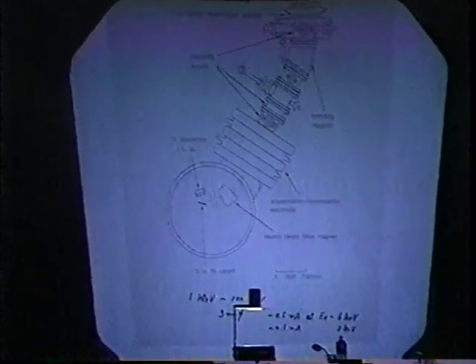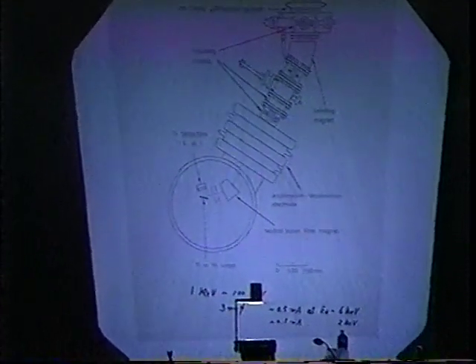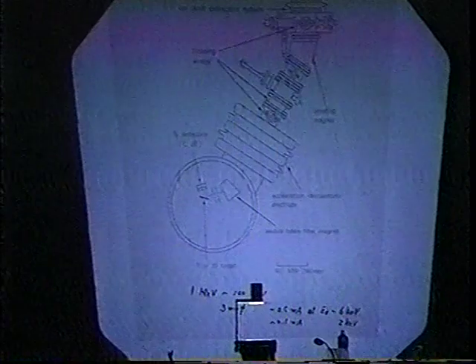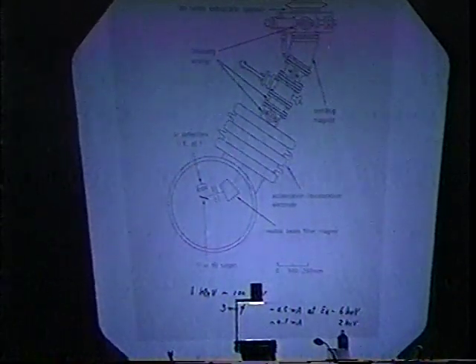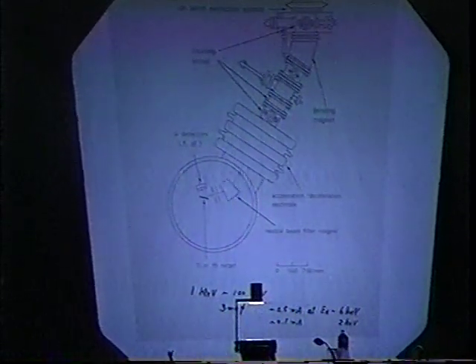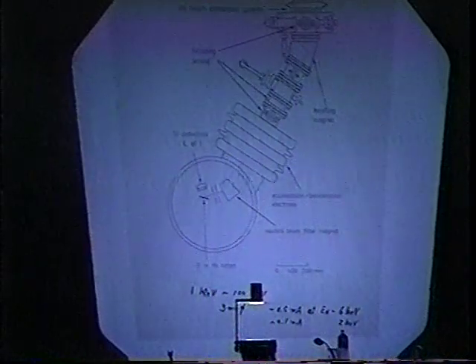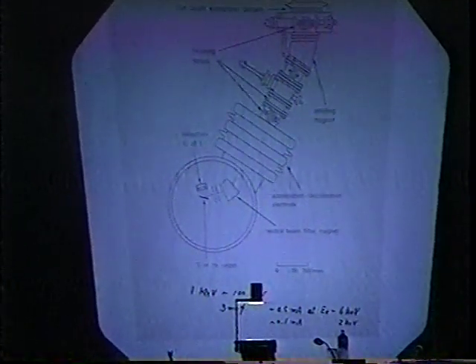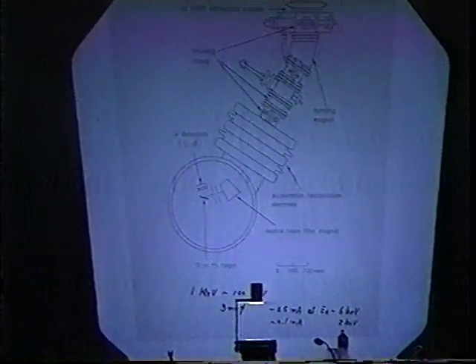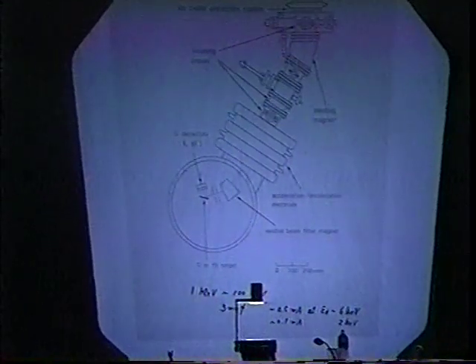Inside the chamber, we put a filter magnet just to separate out the neutral beam, because the ions extracted from the ion source have an energy of something around 20 keV, and during this transport stage the ions can be neutralized. That means they cannot be affected by the deceleration voltage and electric field, so they still have a very high energy. So we put the neutral beam filter magnet here. The real low energy beam is bent by this magnet and hits the target here. And we put the signal detectors here.